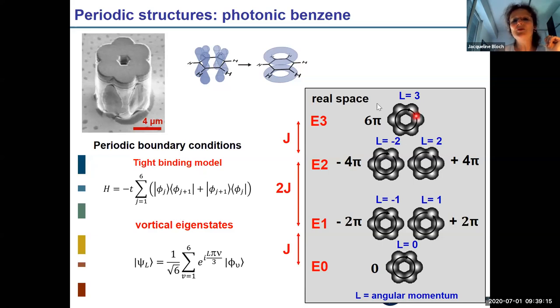So when you compute that, what you find is that you actually have four energy levels, and all the states are collective eigenstates, which are delocalized over the six elementary orbitals. They are a linear superposition of these six orbitals with a complex coefficient, which is labeled by L. The lowest energy state corresponds to L equals zero, and all the elementary orbitals are in phase. The upper state corresponds to L equals three, and then every site is out of phase with its neighbor. And then there are two very interesting levels in between, which are twice degenerate, and correspond first to L equal plus one or minus one, and then to L equal plus two and minus two.